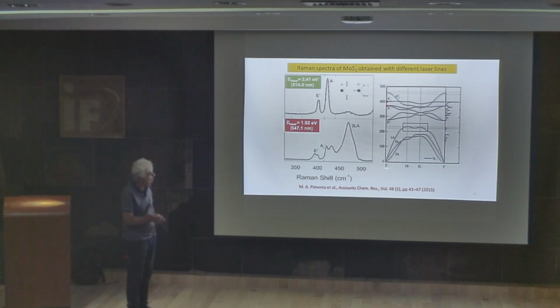And this is the phonon dispersion of molybdenum disulfide. The A and E modes are here at the center of the Brillouin zone. Those are those peaks here. But this 2LA band comes from phonons of the longitudinal acoustic branch near the M and the K point. Here it is 230, but when you have two phonons, we have a higher-order process. Then we have two phonons of 230, so we have 460, and this band has been known for many years. It was related to two times the longitudinal acoustic phonons near the M and the K point.